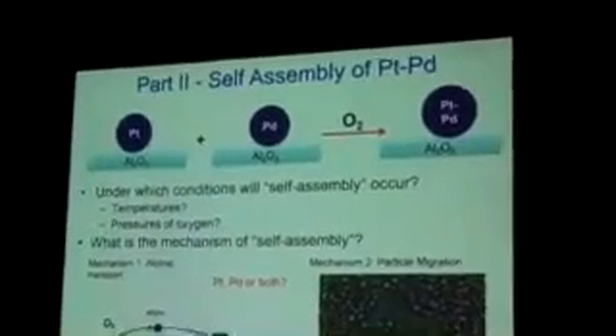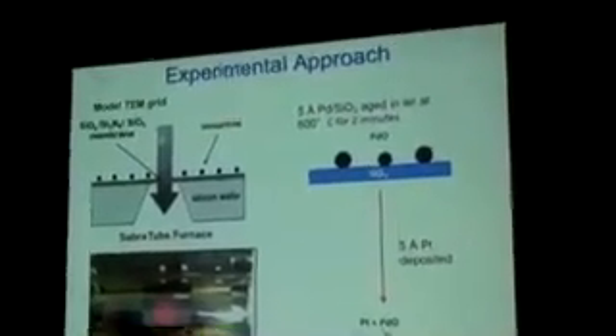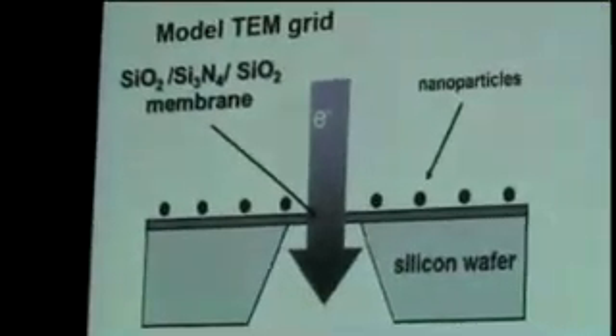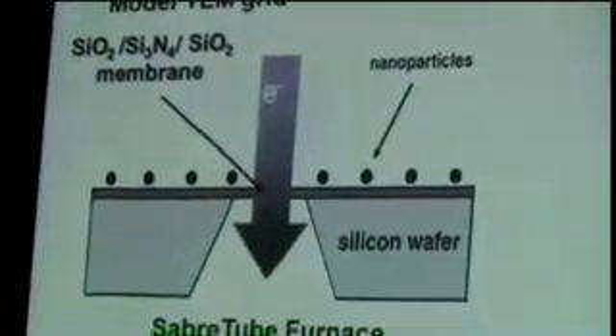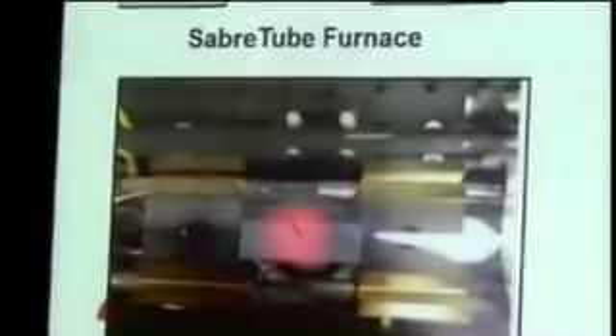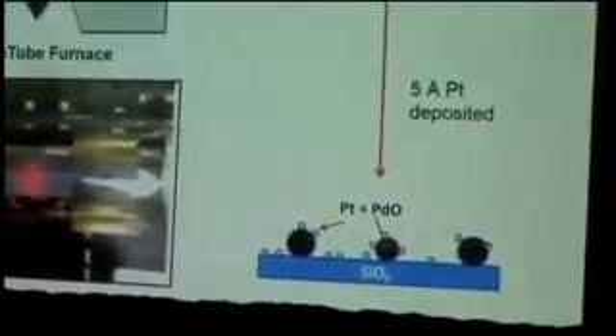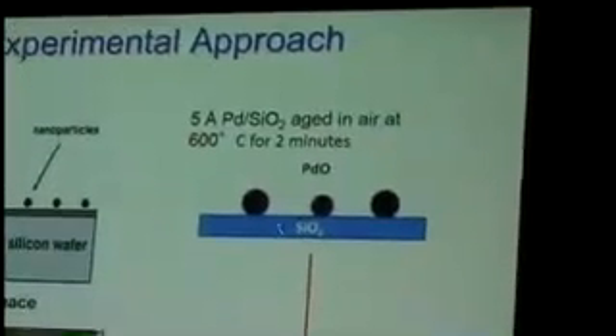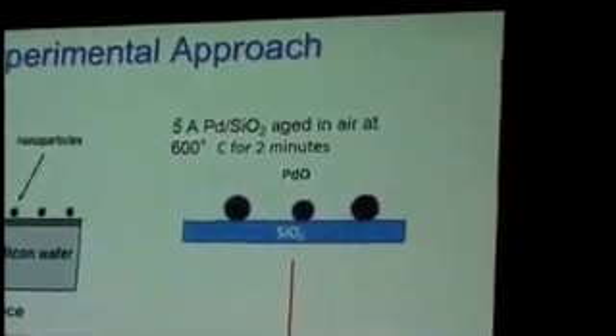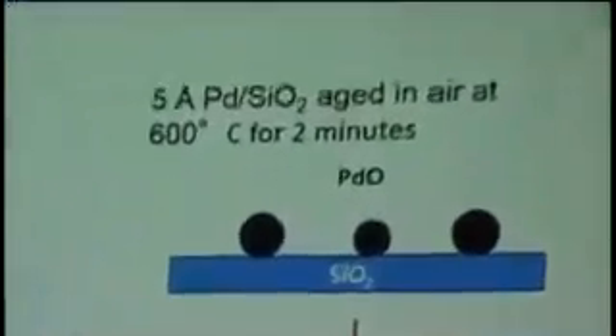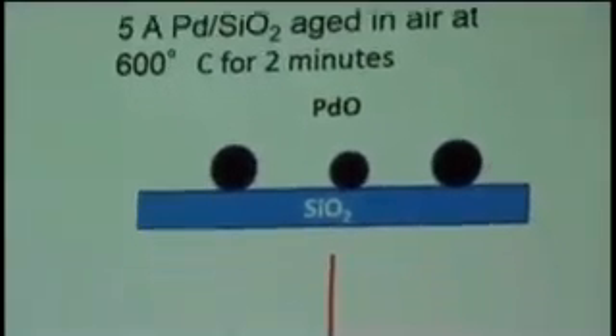So what's the mechanism? Something has to move. So we wanted to study that. We used model TEM samples developed by the Hansen and Burt group. And they also showed us an interesting reactor that allows you to heat samples very quickly and cool them down very quickly. So what we did, we prepared a model sample with the palladium oxide, and then we added a little bit of platinum. And then we just heated it to see what happens.